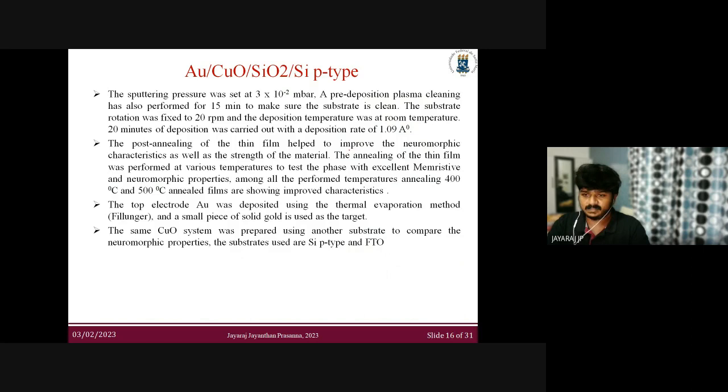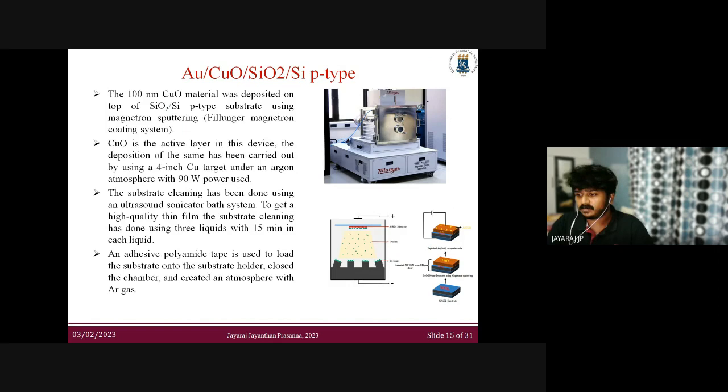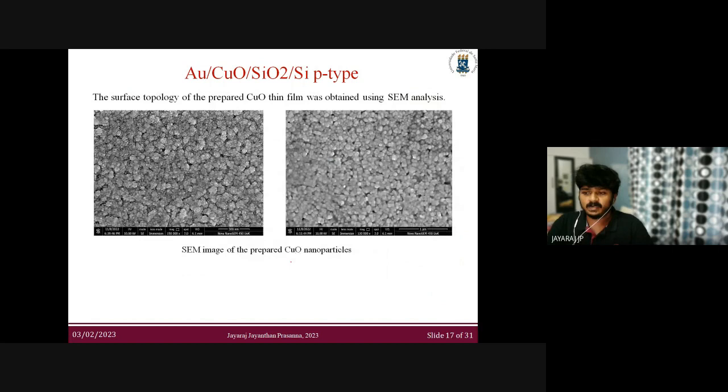I used gold as the top electrode, deposited using a thermal evaporation technique. This is the SEM image of the prepared copper oxide nanoparticles, showing the surface topology. The grain sizes are around 17-18 nanometers.